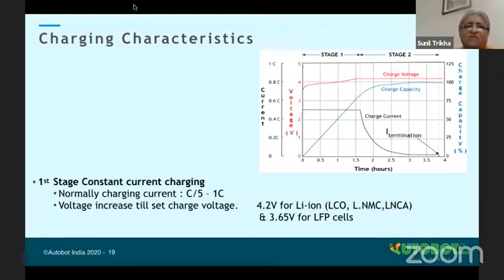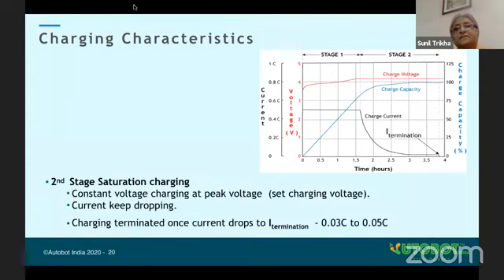Similarly, for an LFP battery, the threshold voltage for this constant potential stage is 3.65. For NCM, NCA, it is 4.2 volt. For LFP, it is 3.65. It's the same as I just explained. So one is the voltage, and the other is the current coming to 0.03 C to 0.05 C. The current is very low, so we stop at that stage. We don't continue charging after that.